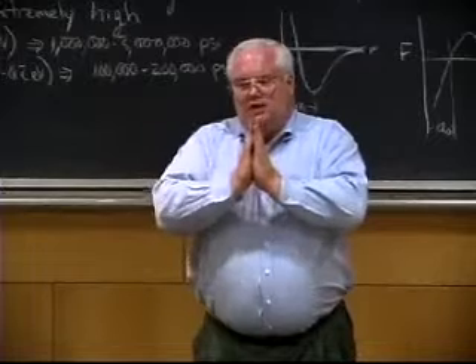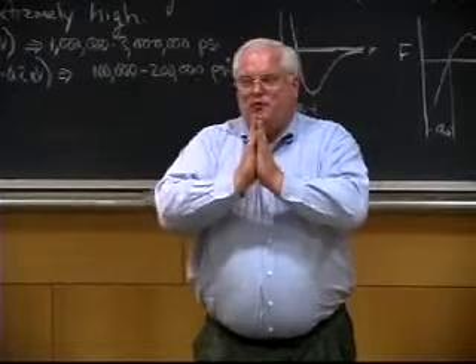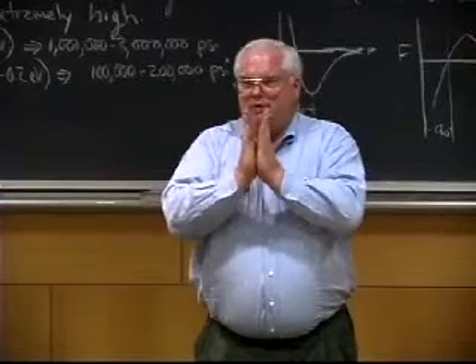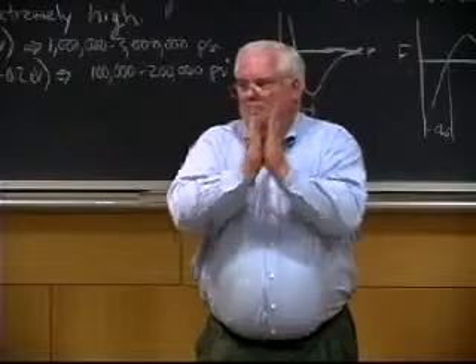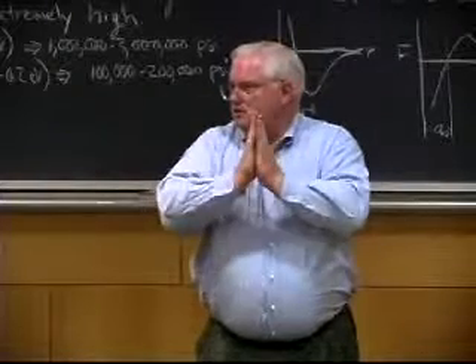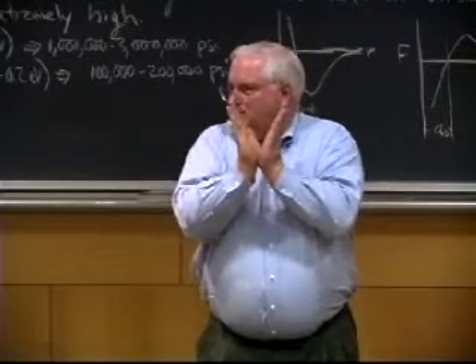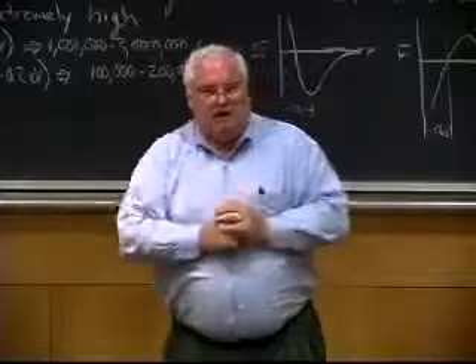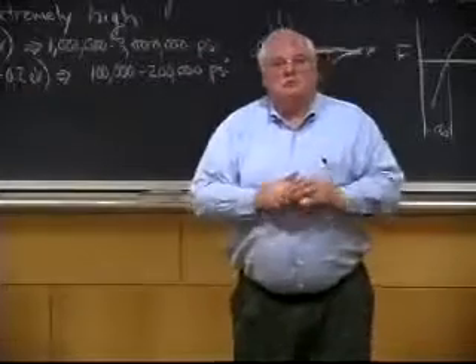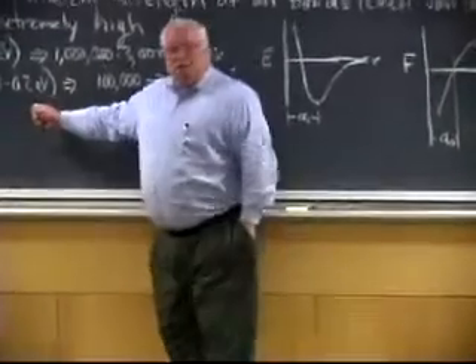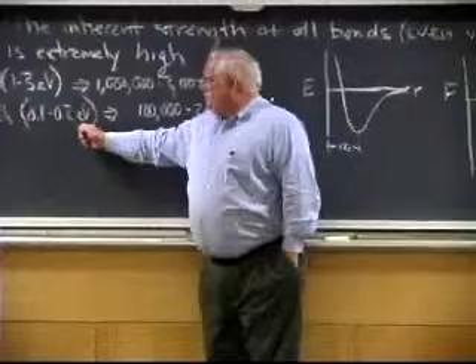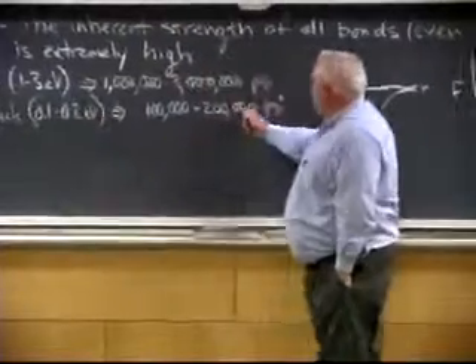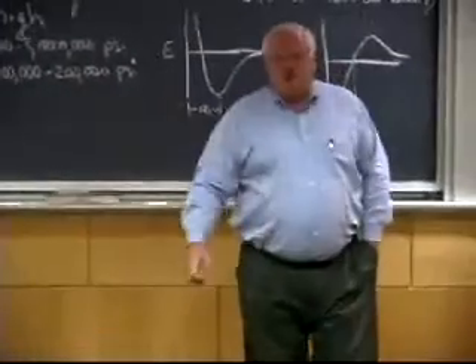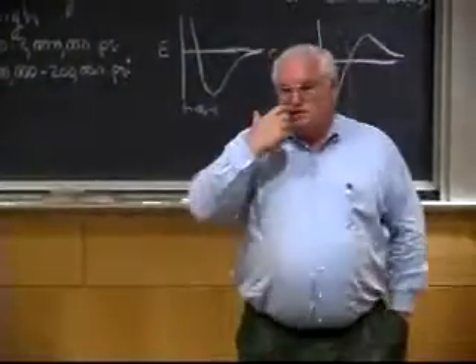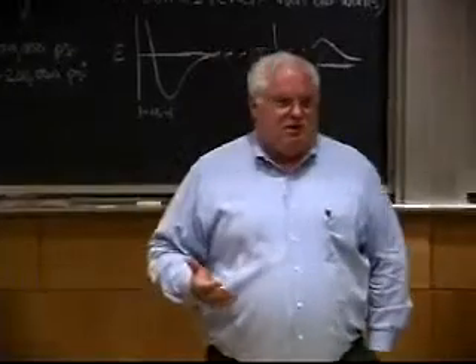In the demonstration of a metal that I did for you, basically you're going to unzip it like a piece of perforated paper. You're not going to break them all at once. You're going to peel them apart. And so you're only breaking one line at a time. Van der Waals bonds, which are about 1/10 to 2/10 electron volts, should in principle have a strength of 100,000 to 200,000 psi. Well, that's the strength of a high-strength steel.